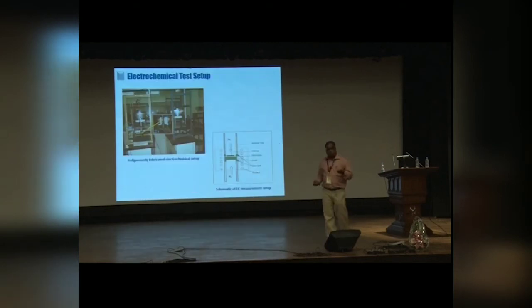But before going to the stack, you need to characterize them. So what we do, we make coupon cells out of the big cells, and we check how good they are. This is the acid test, you can say. On one side we pass hydrogen, and on the other side we pass oxygen. These are alumina tubes, with glass seals, and glass rings we put over here, and then you test it at different temperatures. This is the furnace, a split type furnace, and these two are the alumina rods. Our sample we keep inside this, and we seal it, and then on one side we pass hydrogen and on the other side oxygen, and then we start the testing.